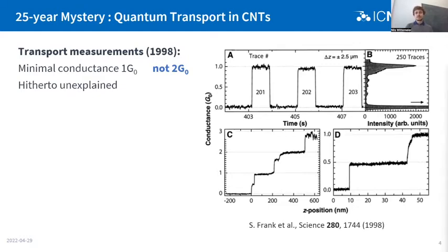and then maybe we go to a multi-layer carbon nanotube, a double wall carbon nanotube, or even more, then the transmission function should still be quantized in multiples of 2g0. It can be more than for a single wall carbon nanotube, but we should expect it to still be quantized in terms of 2g0.